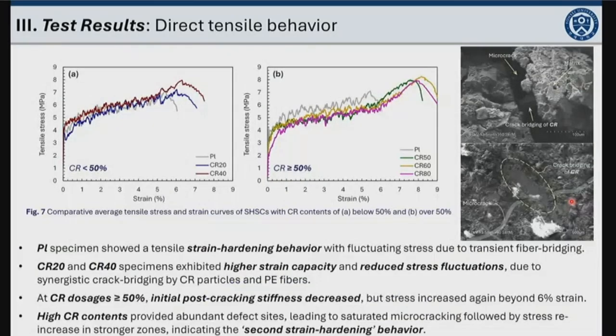This is the average tensile stress and strain curves with various dosages of crumb rubber. The plain sample here exhibited the general strain hardening behavior. By replacing the silica sand up to 40%, even though the tensile performance was improved, there was no change in the shape of the tensile stress and strain curve.